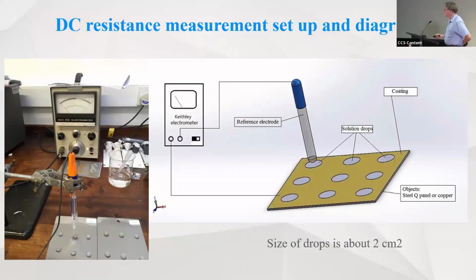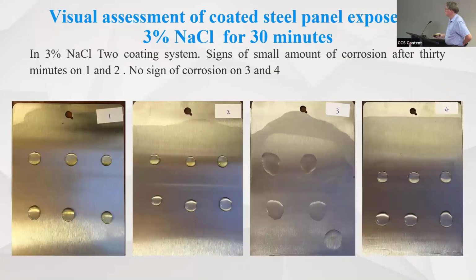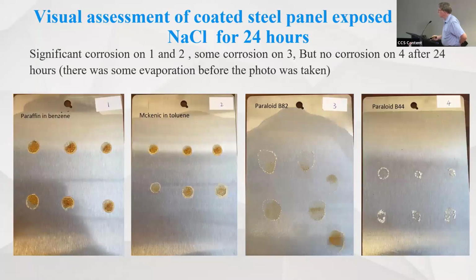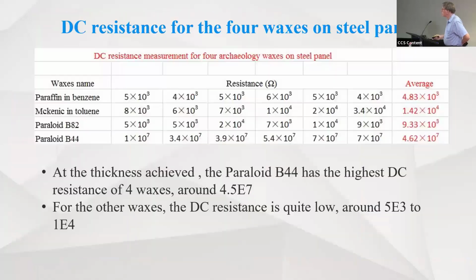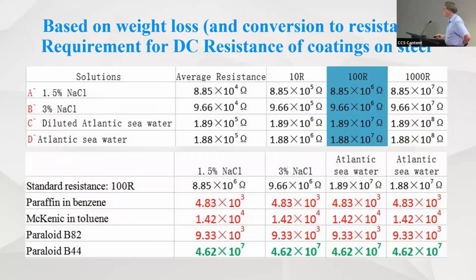And so we did these tests with just simple drop tests to get some idea of the resistance and the corrosion protection afforded. And we then managed to apply those drops to the samples, both copper and steel, and some coatings were doing better than others, and the two-coat systems, as you might expect, were doing better than a single coat, and they were getting some rusting. So we were trying to relate that to our DC measurements, and they did pretty well. The relation was good, in that, as we might expect, the lower values of resistance, as I said, is DC, were related to the ones that corroded significantly, and the ones that didn't corrode at all in a relatively short-term test had much higher resistances. So we were able to give the museum an indication of which were the better ones.